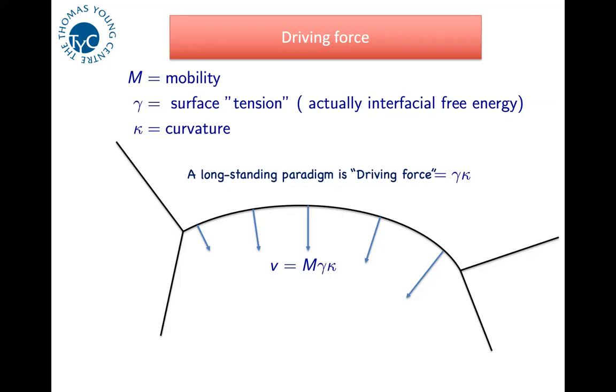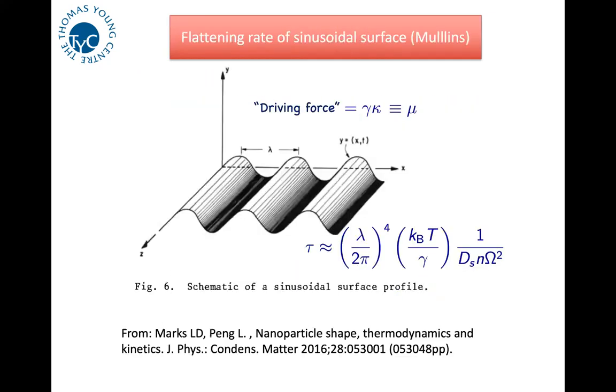And so this can give you a beautiful simulation until, of course, your surfaces are flat, and then it stops. And then you've got to do some other tricks. But the materials theorists have thought of that. But before we go on to that, let's just see how this can operate in practice. If you take a surface and you make a lot of parallel scratches on it, close together, and it heals up, then you can estimate from that what the surface diffusion coefficient is, which is doing the healing and reducing the surface energy. And this is an old model, goes back to Mullins.